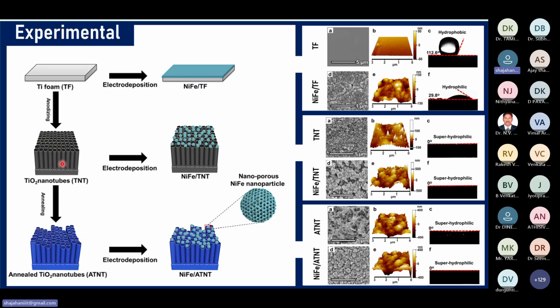TNT is amorphous after anodizing, and it shows low conductivity. Therefore, we conducted annealing to increase the conductivity and crystallinity. Therefore, we attained annealed titanium oxide nanotubes with anatase. Then we electrochemically deposited nickel iron catalyst on ATNT. That we used as an efficient anode material for the AMW. For comparison, we also made nickel iron catalyst on TNT and on TF.